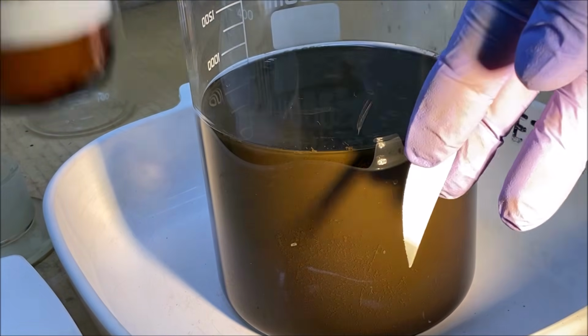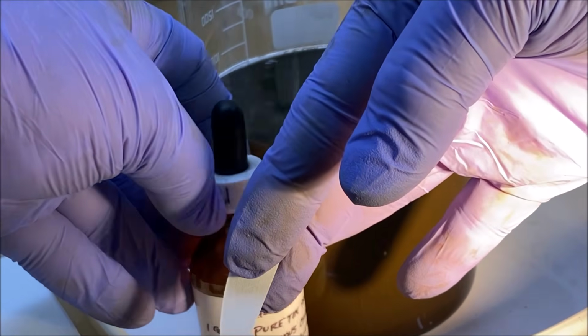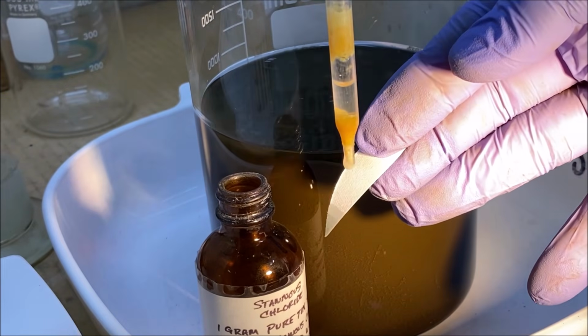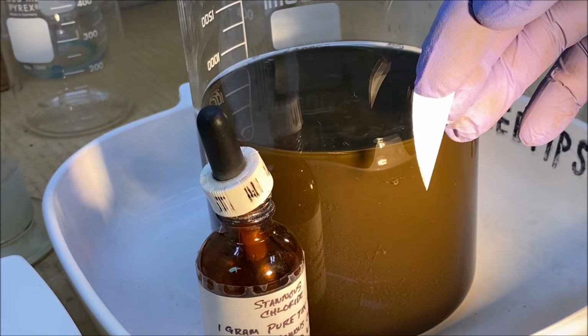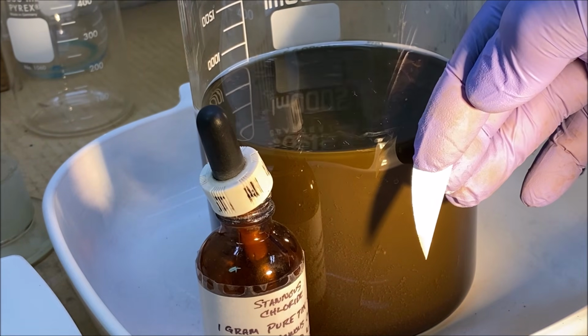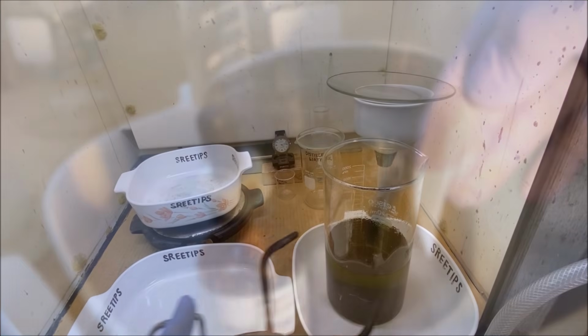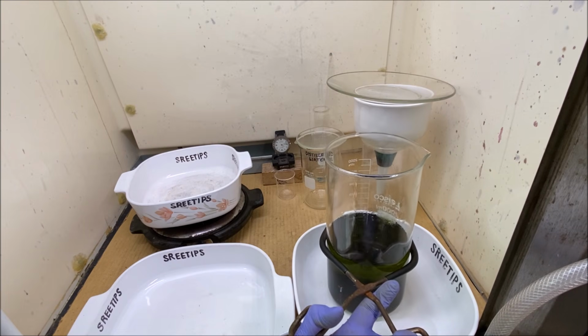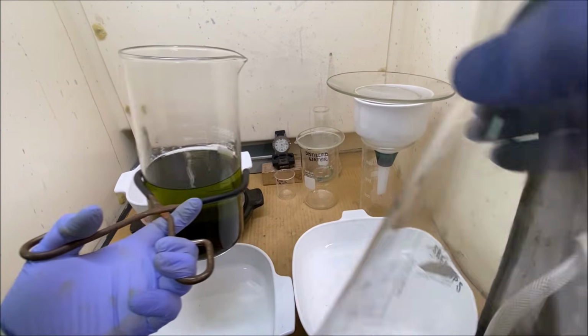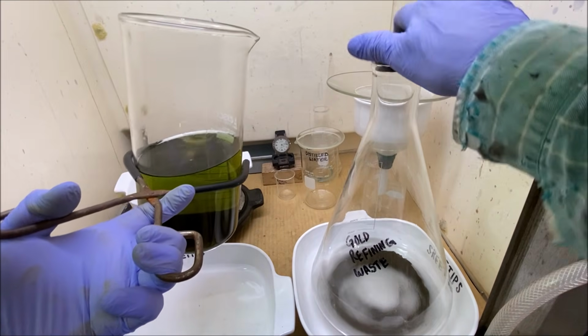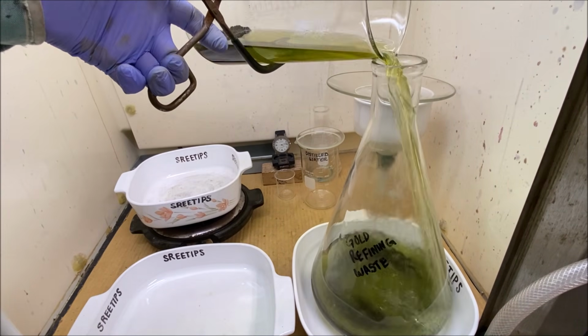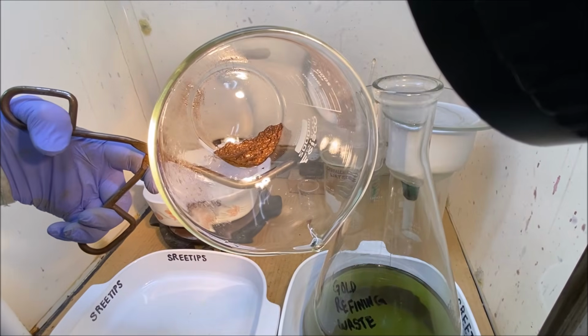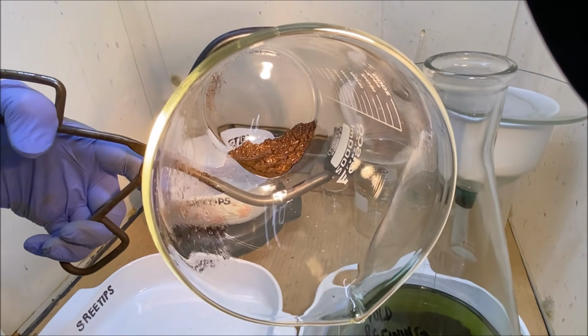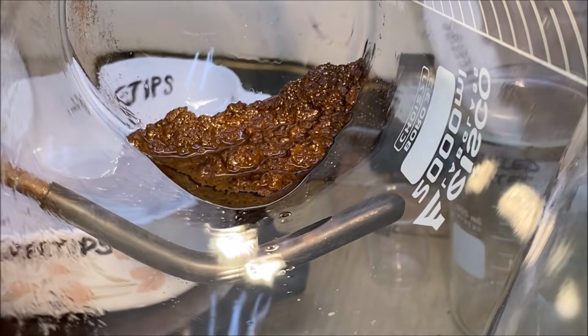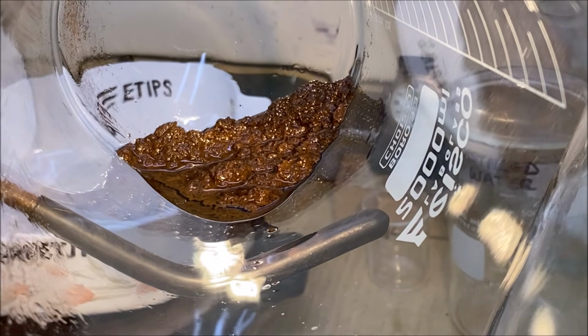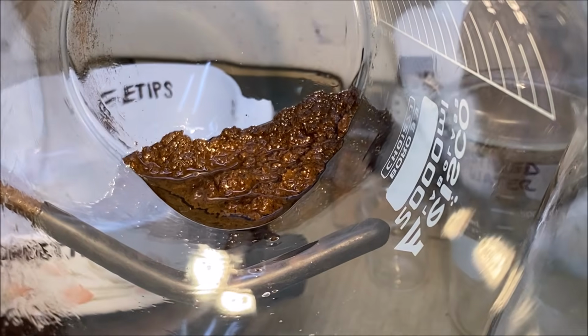Stannous test before we did this precipitation, which I should have done. Maybe one after. You can see by that negative stannous test, all the gold has been precipitated. Let's get this solution poured off of here. It's looking pretty good. Expecting 12 to 15 grams of pure gold from this batch of gold-filled scrap.